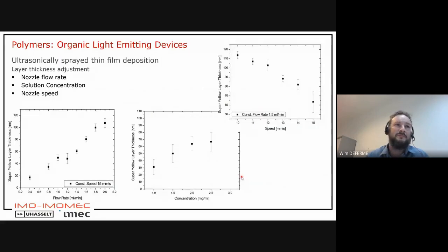So then we started to investigate the influence of the spray coating parameters on the layer thickness. And for example, here you see the flow rate, and you see the layer thickness as a function of this flow rate. And to be specific, we need a thickness for this Super Yellow, for this light emitting layer, of around 80 nanometers. So for us, that means having 1.6 milliliters per minute is an optimum.